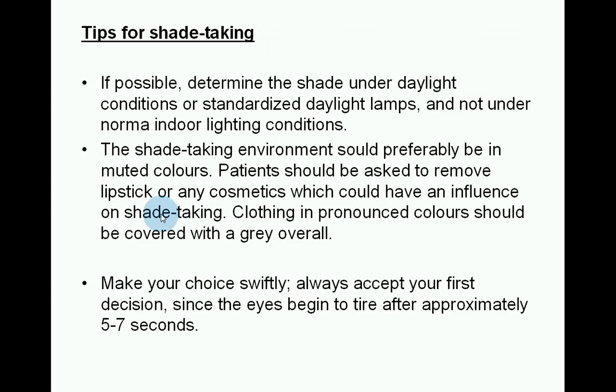Tips for shade taking. If possible, determine the shade under daylight conditions or standardised daylight lamps, and not under normal indoor lighting conditions. The shade-taking environment should preferably be in muted colours. Patients should be asked to remove lipstick or any cosmetics which could have an influence on shade taking. Clothing in pronounced colours should be covered with a grey overall. Make your choice swiftly — always accept your first decision, since the eyes begin to tire after approximately 5 to 7 seconds.